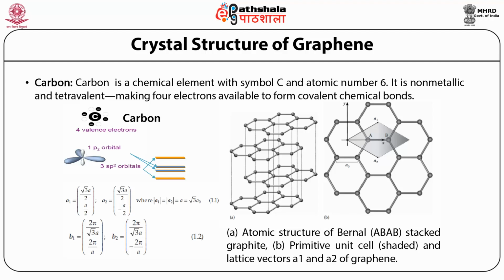Graphene, which is one layer of graphite, is another crystalline allotrope of carbon with two-dimensional properties. Its carbon atoms are densely packed in a regular atomic scale hexagonal pattern shown in figure B. Each atom has 4 bonds, one sigma bond with each of its 3 neighbors and one pi bond that is oriented out of plane. The atoms are about a0, which is equal to 1.42 angstrom, apart.